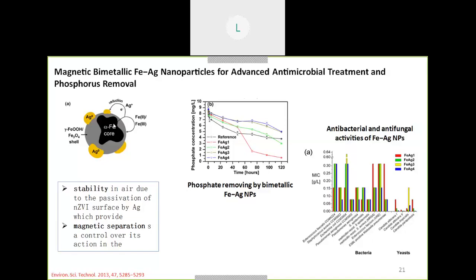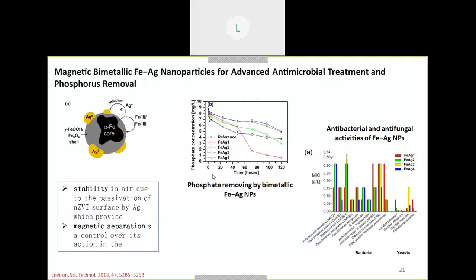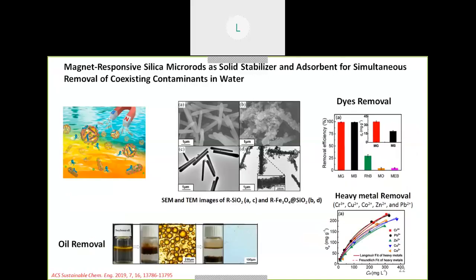So they were able to get results of almost 95% phosphorus removal, and they have shown antibacterial activity against many species. This one is another example where nanotechnology enabled these people to synthesize such materials where they can easily get three types of application in one go. What they did, they synthesized an iron based material, a capsule coated by the silica rod, coated by iron like magnetite nanoparticles.